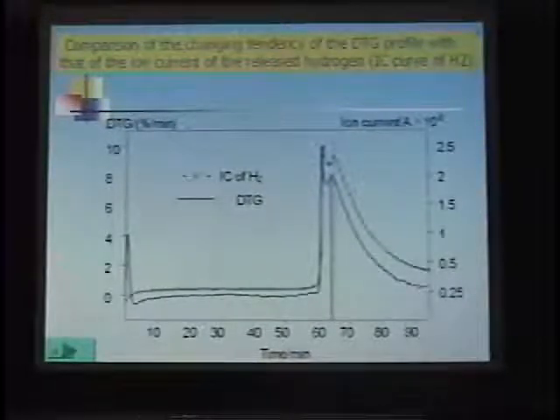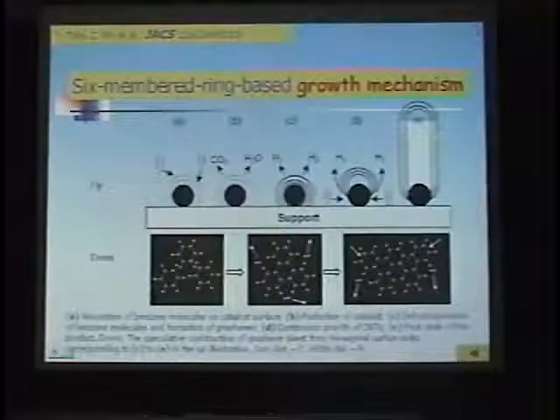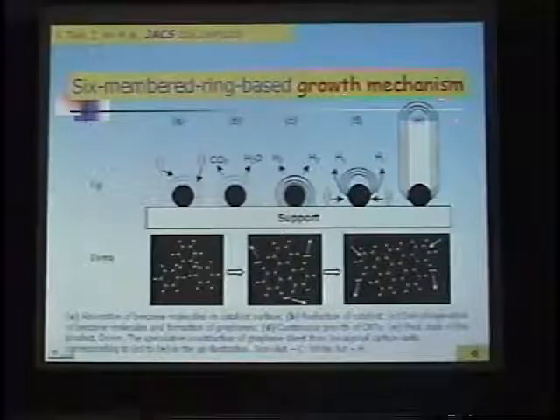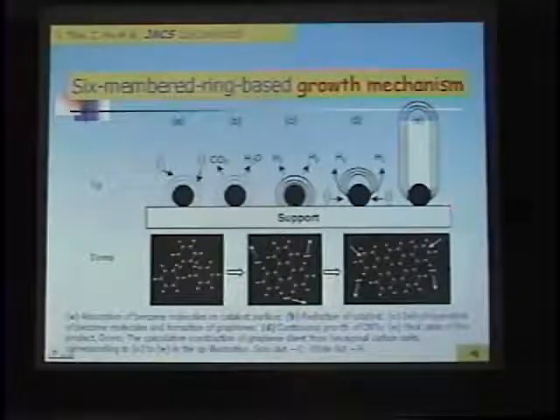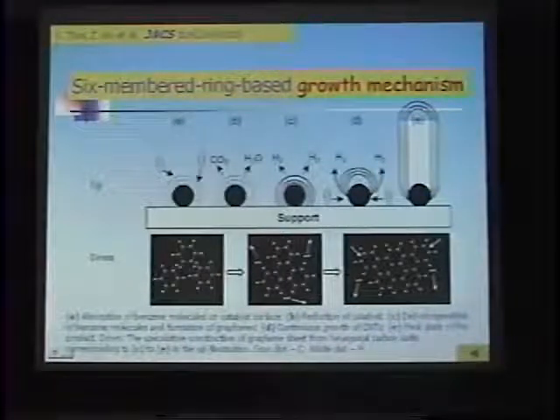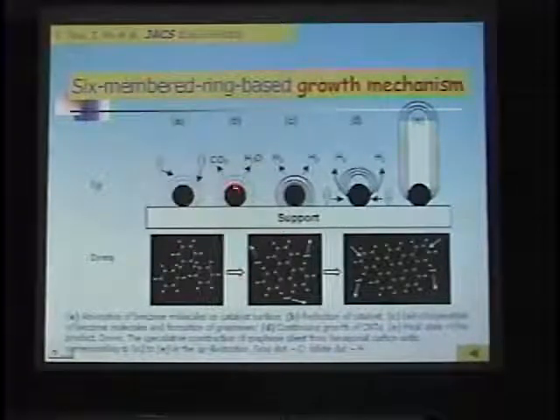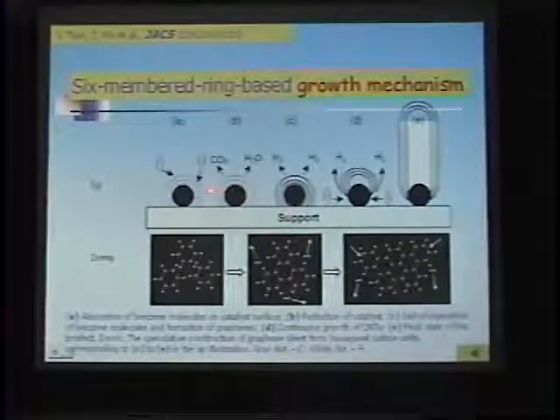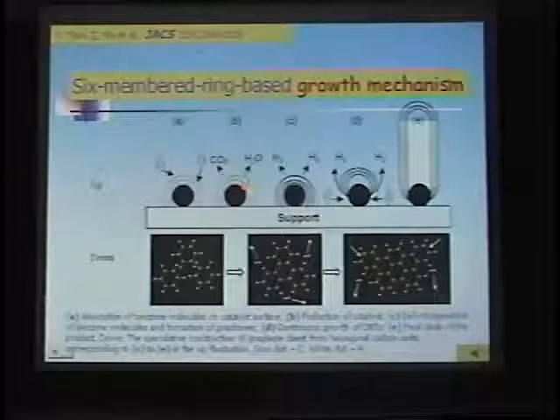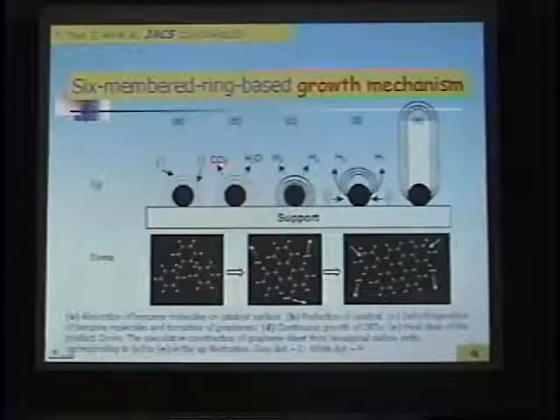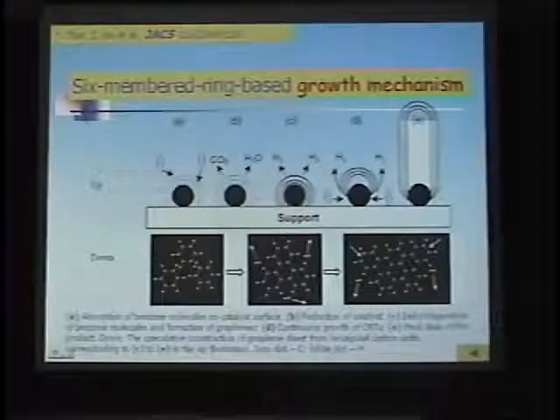So by the integration of all the experimental data, we could get the six-membered ring-based growth mechanism. That's exactly what we expected. The only difference is that the original state of the catalyst is an oxide state, so there is a reduction step at 640 centigrade. Then we could detect a little carbon dioxide and water, since there are reactions like that.